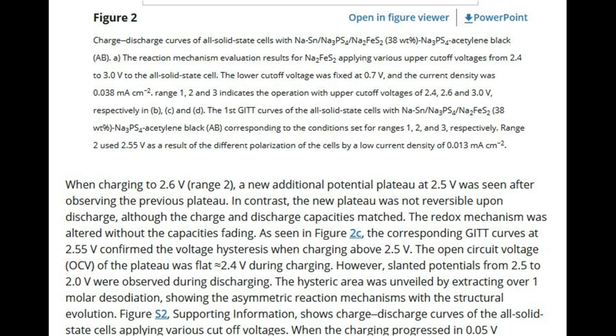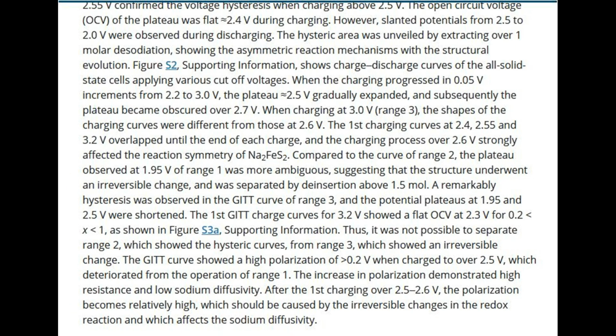When the charging progressed in 0.05 V increments from 2.2 to 3.0 V, the plateau at 2.5 V gradually expanded, and subsequently the plateau became obscured over 2.7 V. When charging at 3.0 V, range 3, the shapes of the charging curves were different from those at 2.6 V. The first charging curves at 2.4, 2.55 and 3.2 V overlapped until the end of each charge, and the charging process over 2.6 V strongly affected the reaction symmetry of Na2FeS2.